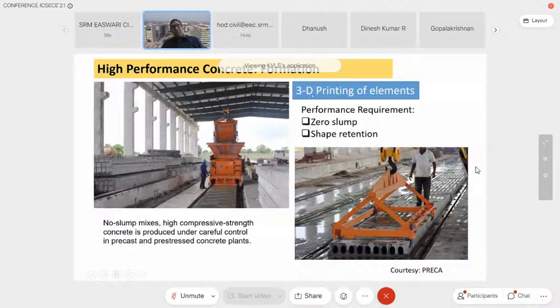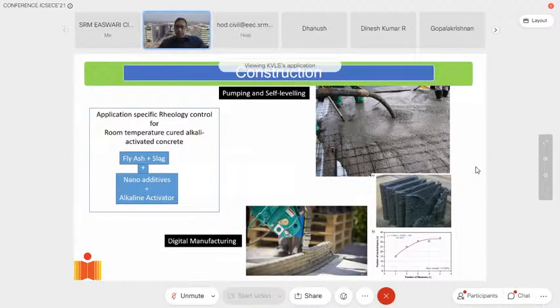If I can now perfect this art, then I can start building my structures by printing them, giving them the shape by depositing layers, and that's typically how concrete printing is done. Now, in terms of concrete printing, you see the slide on the right-hand side here. We're currently looking at extrusion-based concrete printing. So here, we build a structure layer by layer. So we discretize the entire structure. You look at a CAD drawing of a building, we break it up into layers, and then we assemble the structure by adding one layer at a time.